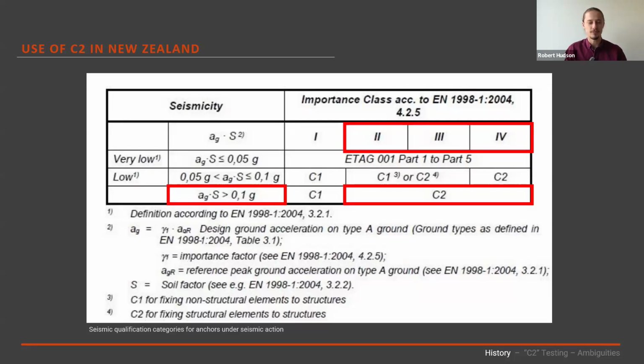It does give you slightly different results if you compare it directly to 1170. But as a general rule, for the vast majority of what we're doing in New Zealand, we have a seismicity greater than 0.1 G. And unless you're dealing with an importance level 1 building, or a shack at the very top of the North Island, you're almost certainly going to be required, following our code, to be using C2 capacities. And that's the situation we're in, and why this is really front of mind for so many engineers in New Zealand.